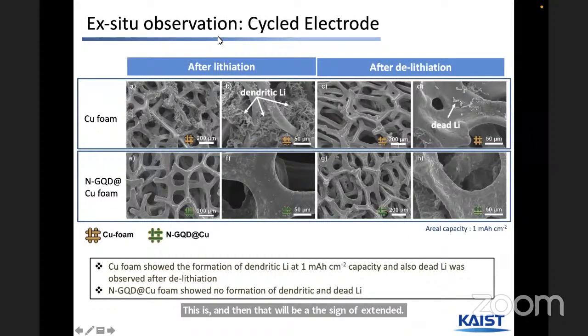So if we look at observations after a few cycles, in the copper foam, after lithiation, you can see how lithium has been deposited on the metallic copper foam. In higher magnification, very well developed dendritic lithium can be observed here.